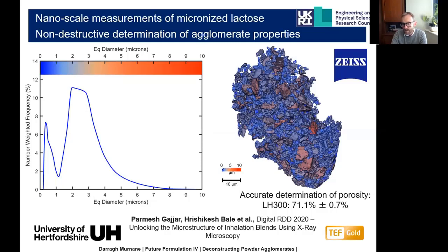We can also start to calculate out the porosity of this, and we can see that there's a porosity of about 71%. So really, there's only almost 30% of this agglomerate which consists of the particles, but yet it's very resistant to being broken up in the airflow and during the blending processes.